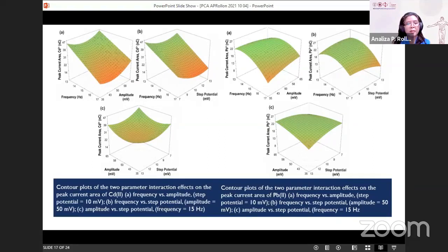And for the optimization, these are the contour plots giving us the two-parameter interactions, for instance, frequency versus amplitude, frequency versus step potential, and amplitude versus step potential. You can see here that the frequency is somewhere between 13 and 15, and step potential near 8, 9, 10. That's also true for lead. And for the amplitude, it's somewhere near this.